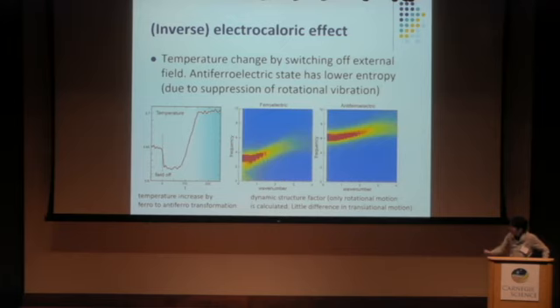This is because the antiferroelectric phase has much lower entropy than the ferroelectric phase, and this can be clearly seen in the dynamic structure factor. This dynamic structure factor is calculated using only the rotational fluctuation, not taking the translational motion into account. We confirmed there is little difference in translational motion. The difference in entropy between the ferroelectric and antiferroelectric phases largely comes from the difference in the rotational vibration.